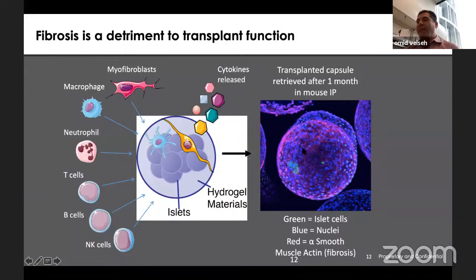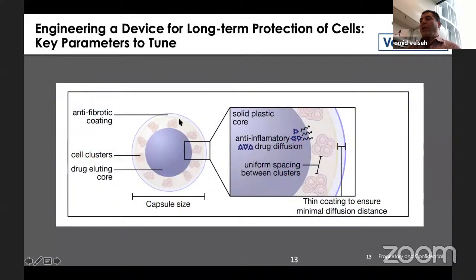onto these hydrogel capsules that now is a barrier to diffusion of oxygen and nutrients into the capsules. And so your transplanted cells essentially starve and are killed off. And that's when the therapy stops working. So we thought about different ways to improve outcomes. And one of the areas we particularly focused on was creating an anti-fibrotic alginate.